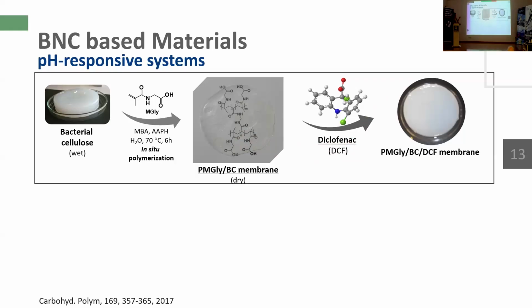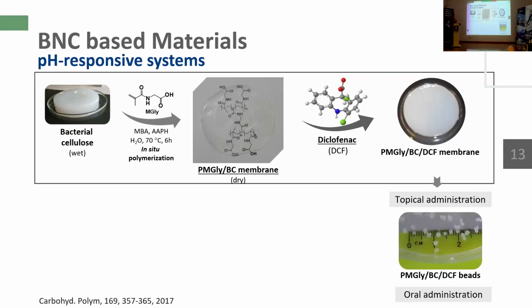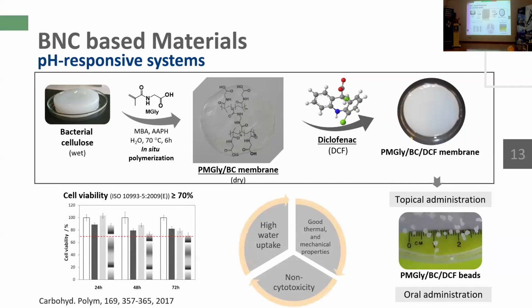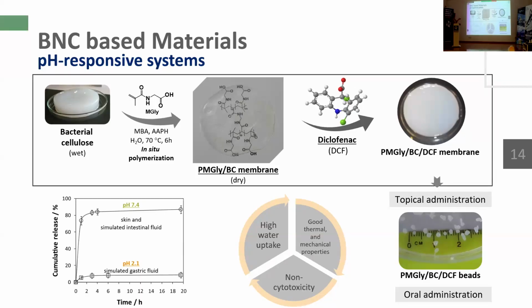And after that, we include a drug, in this case, diclofenac, that was used as a model drug. We also prepared beads aiming at oral administration, but in any case, these systems present high water uptake, good thermal and mechanical properties, are non-cytotoxic toward human cells, but most important, we are able to obtain a pH-dependent release. That was what we intended, particularly for oral administration, to avoid the effects of the first passage in the stomach.